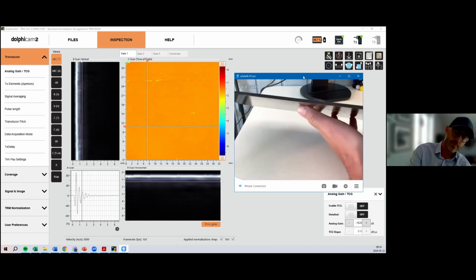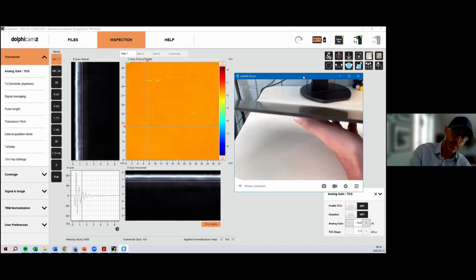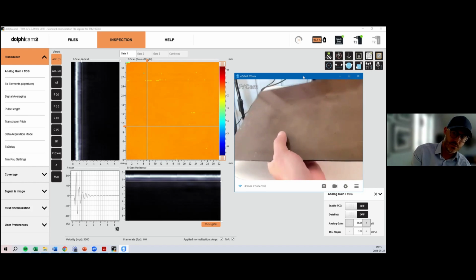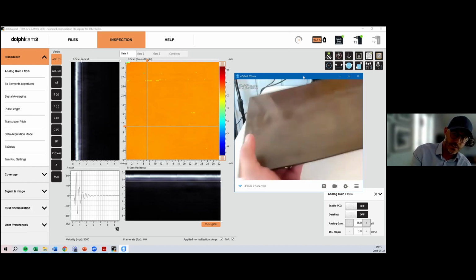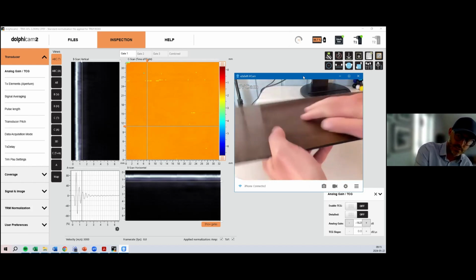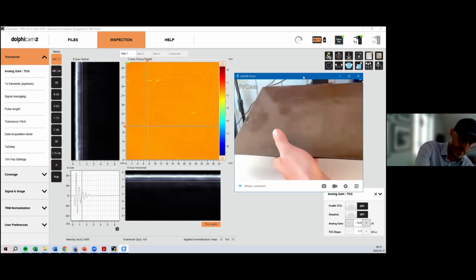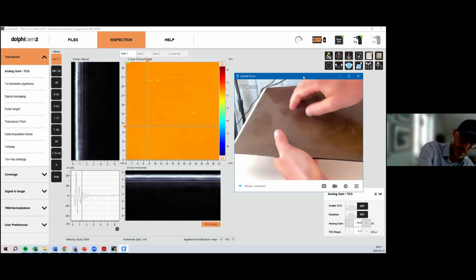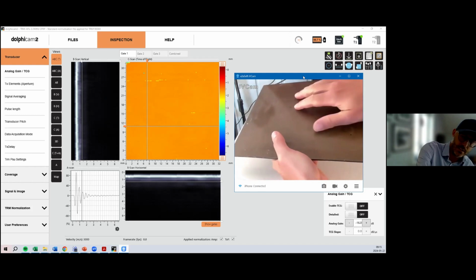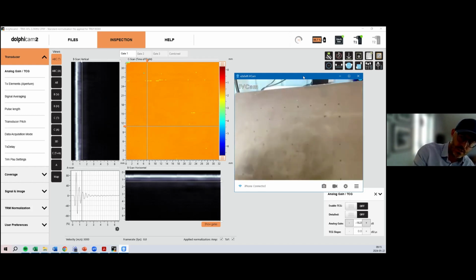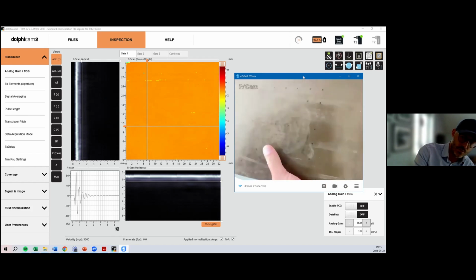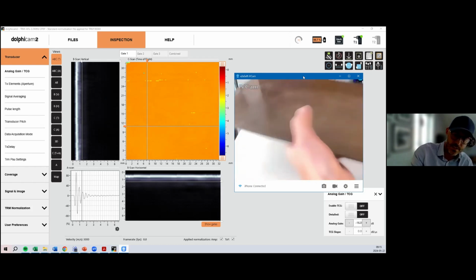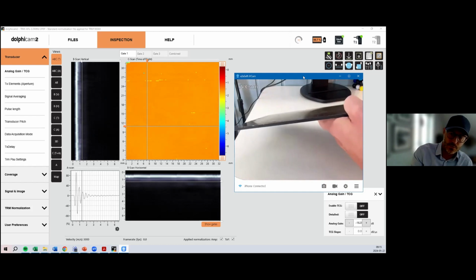So this is a 4.5 millimeter piece of a composite, and it's very, very strong, but also very light. It's very strong in this direction, but what has happened to this one, we've put impact damage on it to make this break inside. But as you can see, you can't really see it on the outside. Now this is worn out a little bit because I've used it for 10 years to inspect, but very strong, very light material.